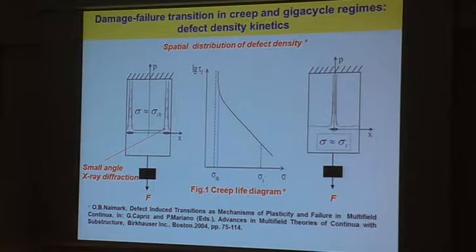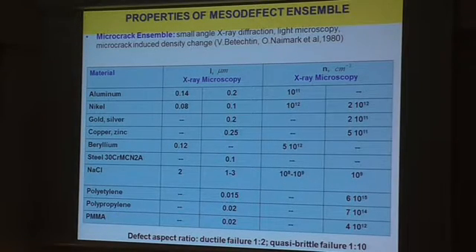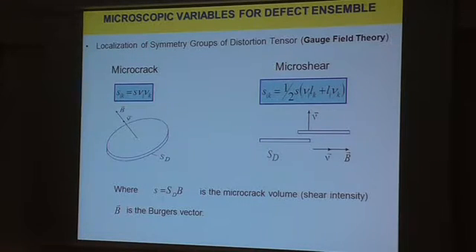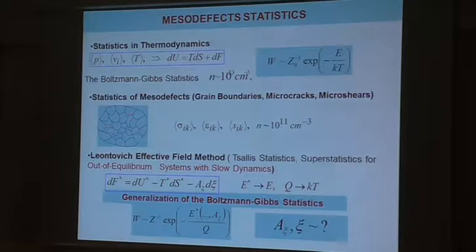In parallel, a field description for this phenomenon was developed, and the background of this field description was also a result of in situ observation of characteristic defects under creep conditions, concerning characteristic size and concentration. It was obvious for us, but it was of course linked with another area of activity because it's very important also for the prediction of shock material behavior. A statistical theory of typical defects with corresponding modes was developed.